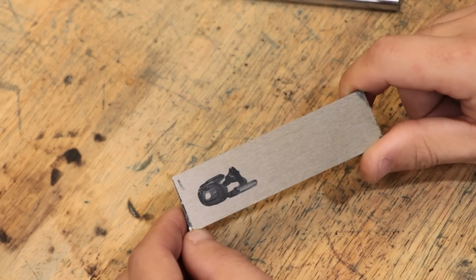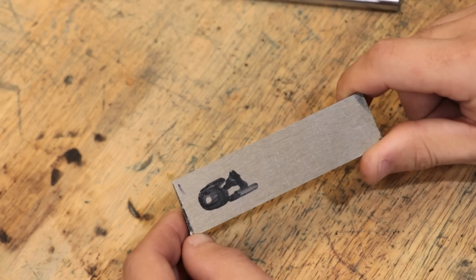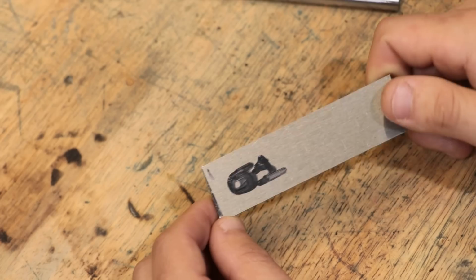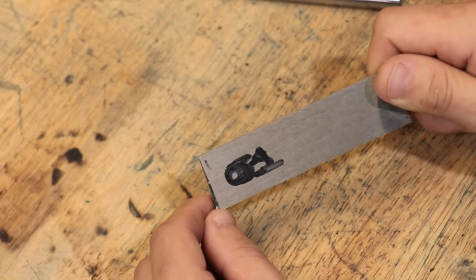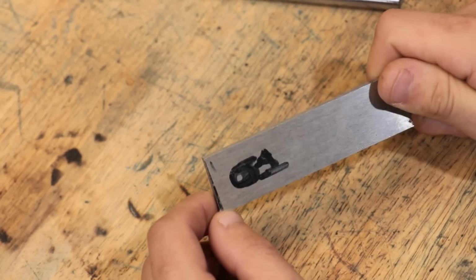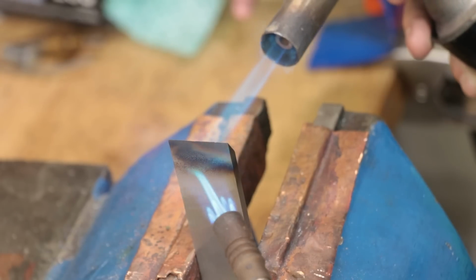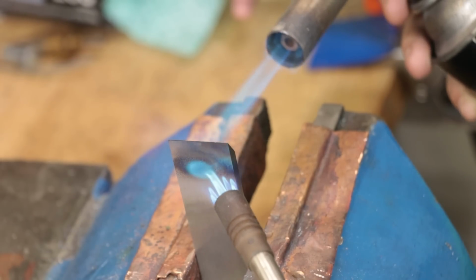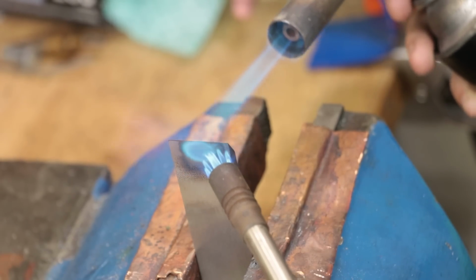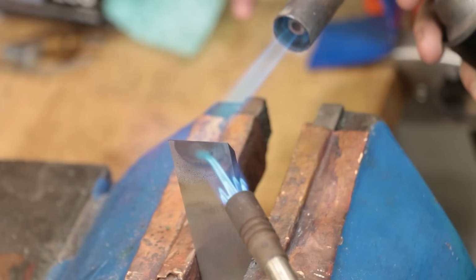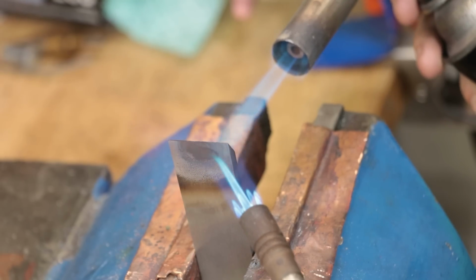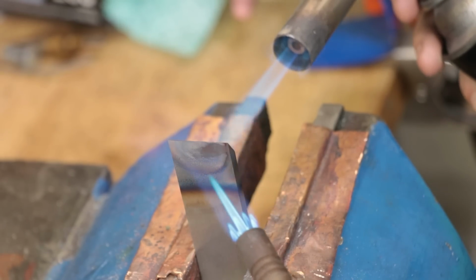So effectively what this means is that the temperature we heat it up to, hold it at, and for how long can be very important when heat treating these types of alloy and tool steels. If we underheat it or undersoak it, it can result in incomplete martensite transformation, but if we overcook it or overheat it, it can result in a lot of retained austenite, and that'll reduce the hardness.